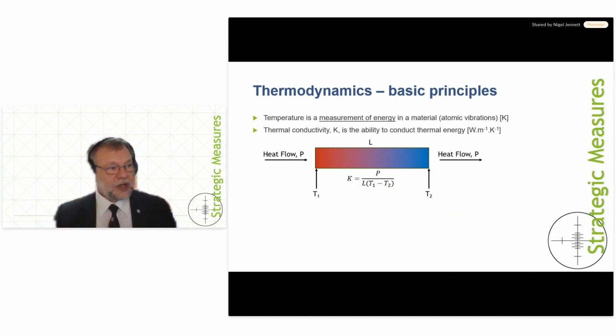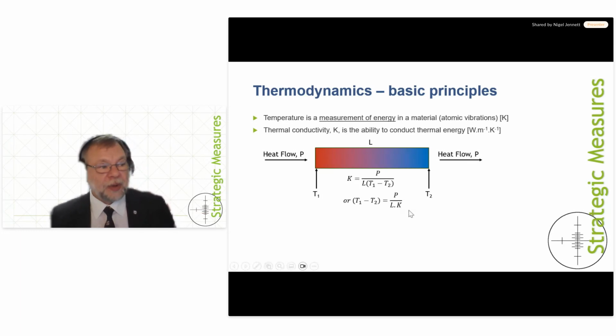And now, if you rearrange that equation, what you see is that the temperature difference that you see, which could be from a heater to a surface, a heater to a tip, the inside to the outside of an insulator on your hot zone, now depends upon the thickness or the distance L and the thermal conductivity, and then you get the power that is taken out. So if you put insulators in the way, you can reduce the power for the same temperature difference. Or, the temperature difference that happens for a particular power that's taken out, you've got the fixed power that you're taking out, is dependent upon the thermal conductivity.